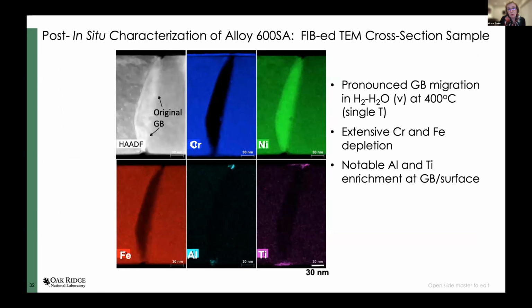So with the sample, what we can do is cut it. Afterwards, it was thick. This was about 250 nanometers in thickness, pardon. And we can see that our boundary was a little displaced, but we've got our chromium oxide film on the surface, chromium depletion, nickel enrichment, iron depletion, and amazingly, evidence that the titanium and aluminum were important in this as well, that these oxides have formed.